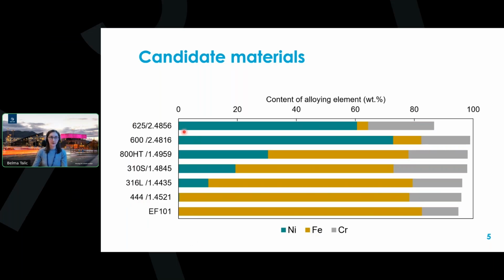In this plot, you can see the main alloying elements, so nickel, iron, and chromium content in the different alloys. And as you can see from the plot, we try to cover in this test campaign a range of different compositions spanning from high nickel and low iron content on the top here to low or no nickel content and high iron content in the bottom.